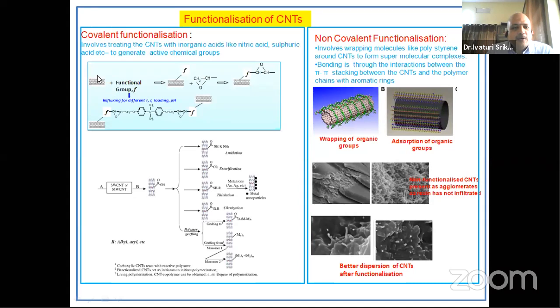So similarly, nanotubes have got a very high strength, but to tap that potential of nanotubes, you have to add some functional group to the nanotubes. So for that, there are different types of functionalizations that are possible, different groups: amine groups, ester groups, acid groups, and all these things. But as the workhorse resin system or the binder is epoxy, amine groups are the most popular functional groups on the nanotubes. Amine functionalized nanotubes are most widely used in most of the applications for aerospace.